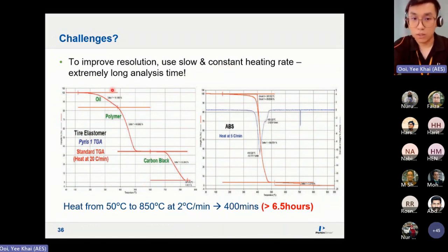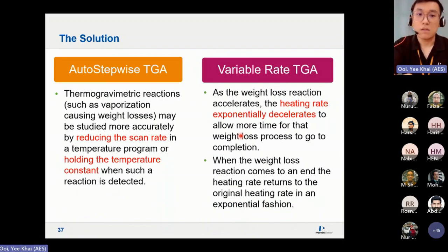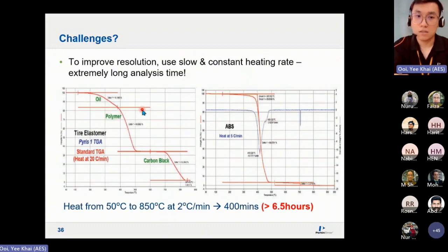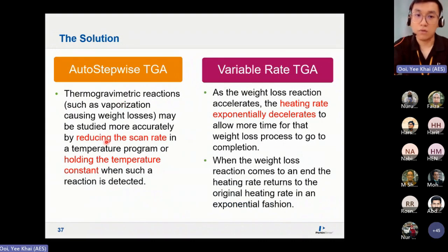But if you do this, you can see from 50 to 850 at 2 degrees C per minute, one sample costs you 7 hours. It doesn't even make sense, right? So too long. What we came up with is, for auto stepwise TGA, when there is no weight loss, you can go fast, or use a higher heating rate. When it encounters weight loss, you can reduce the scan rate to a small scan rate to optimize the resolution, or you can even do isothermal. Until the decomposition is completed, it will revert back to its original heating rate again.